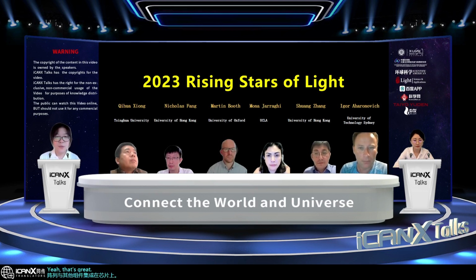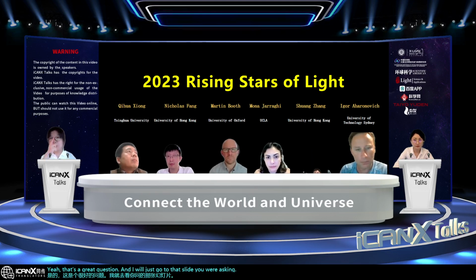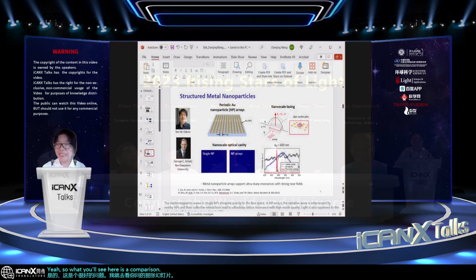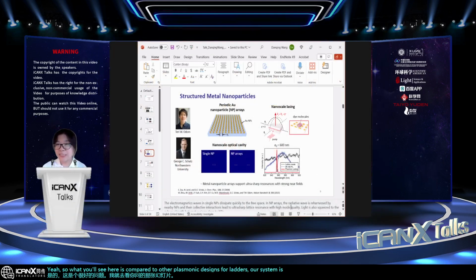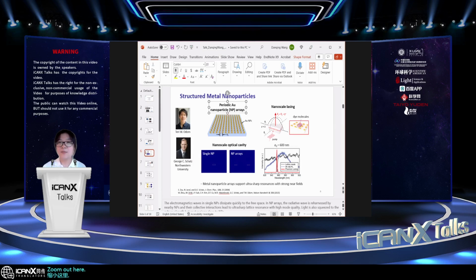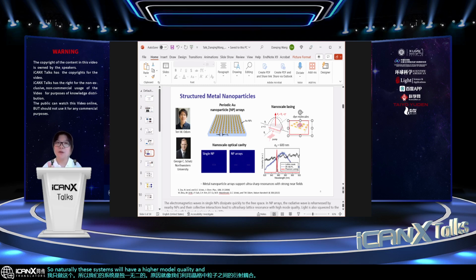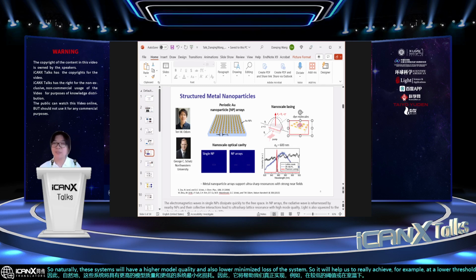Yeah, that's a great question. And I will just go to that slide you were asking about. Yeah, so what you see here is that compared to other plasmonic designs for lattices, our system is relatively unique. The reason is we're harnessing this diffractive coupling between the particles in the lattice. So naturally, these systems will have a higher quality factor and also minimized loss. So it will help us to really achieve lasers, for example, at lower threshold or at room temperature operation, which is beneficial for integrated photonics.